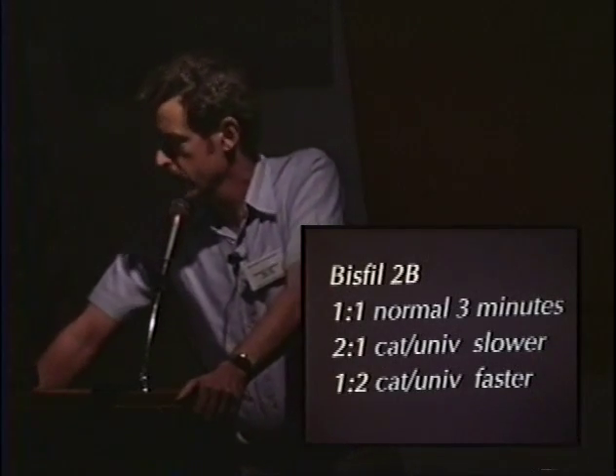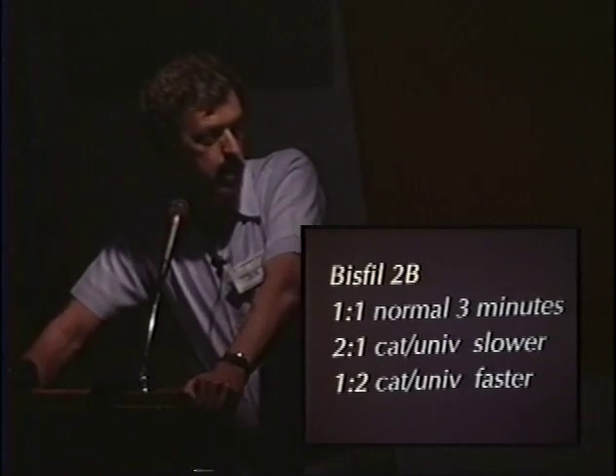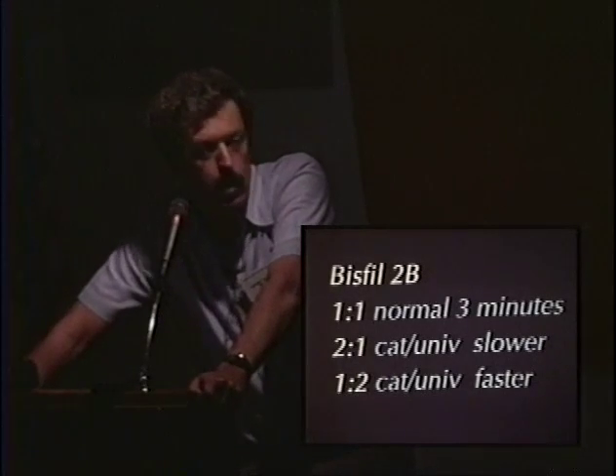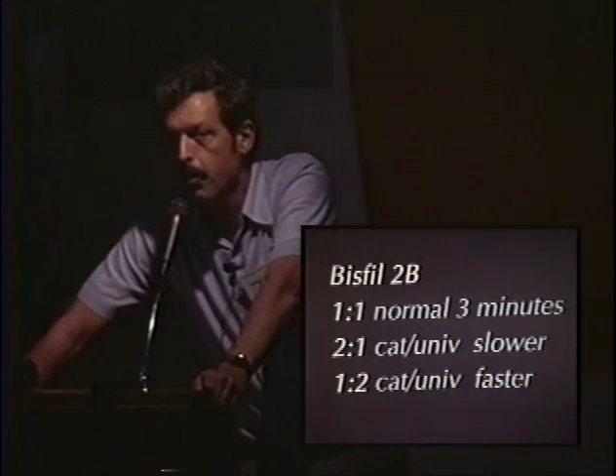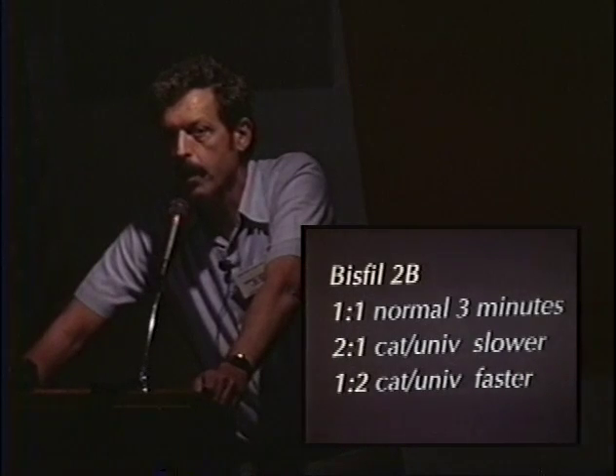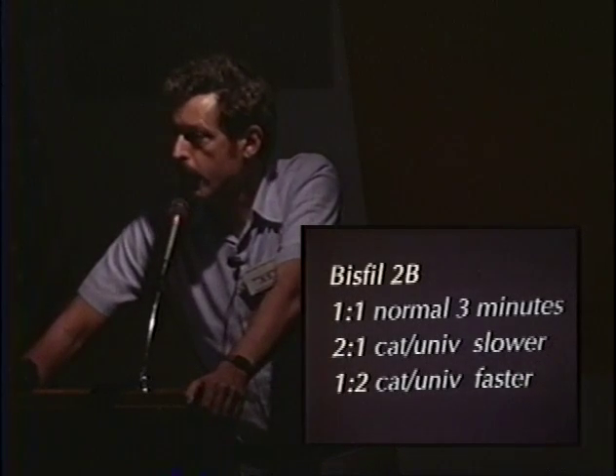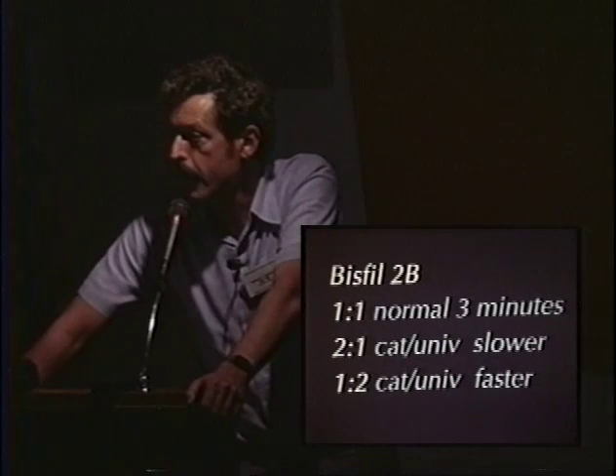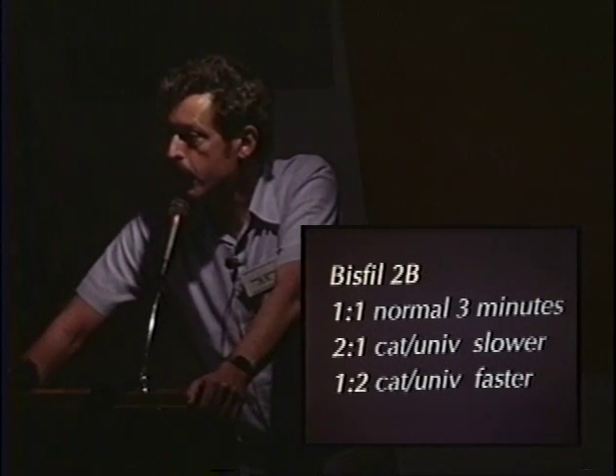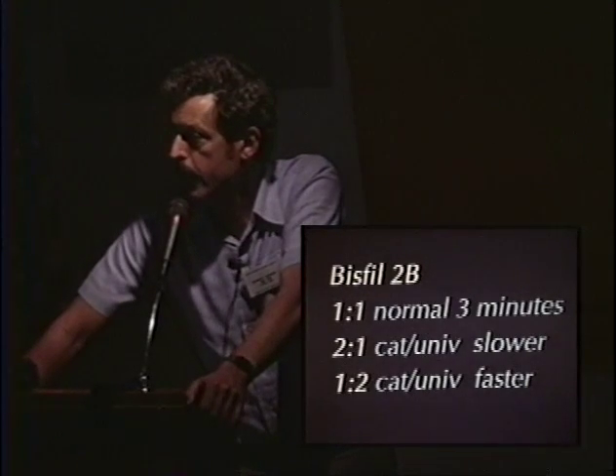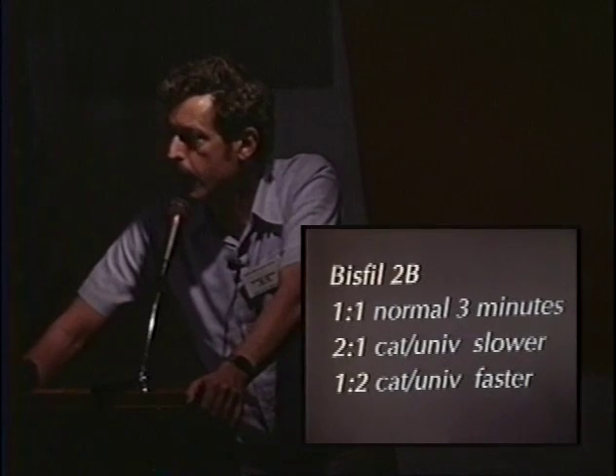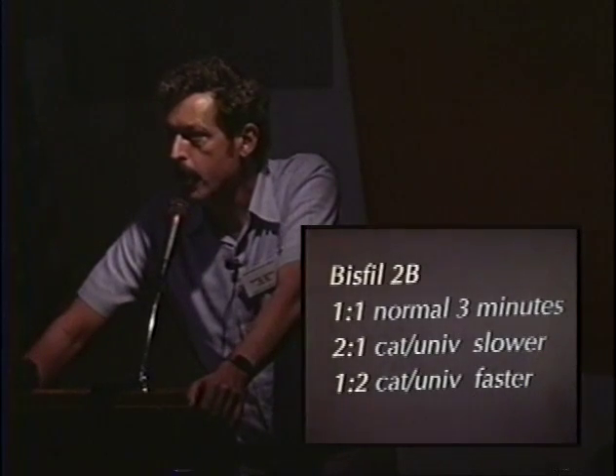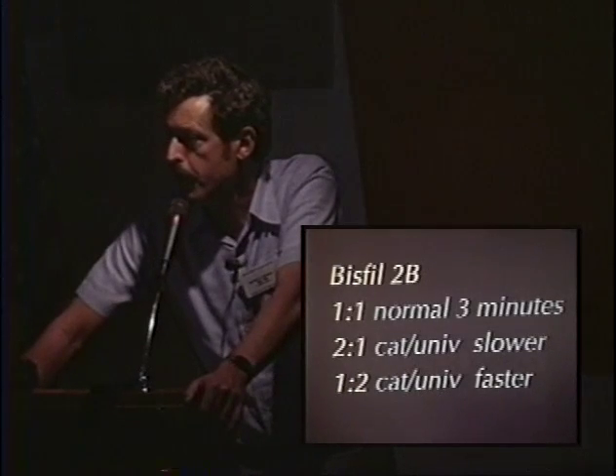Yeah? What are you doing when you have the interproximal roll around at the facial and it's maybe a bypass facial? If the interproximal goes around the facial and you don't want an ugly line there, what you do is you take a little Herculite or Helio, pack it up against a matrix band, staying off the dentin, go ahead and cure it, and then inject in Bisfil behind it. And if it's that wide of a prep, you shouldn't have too much trouble doing that. It's a little tricky, but it'll work out okay. You can just inject in some Helio in there and then push it with some kind of metal instrument and then go ahead and inject behind it, and that's fine.